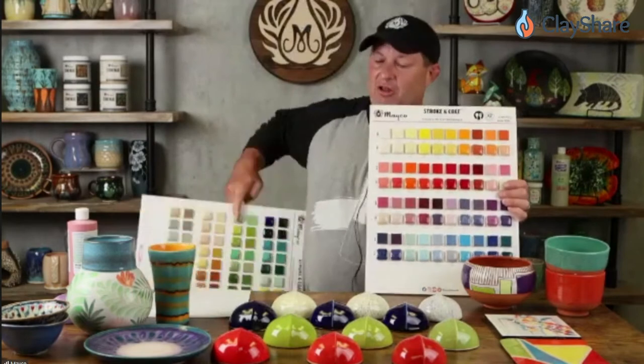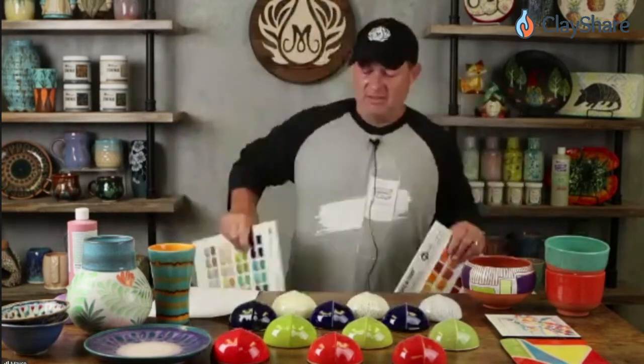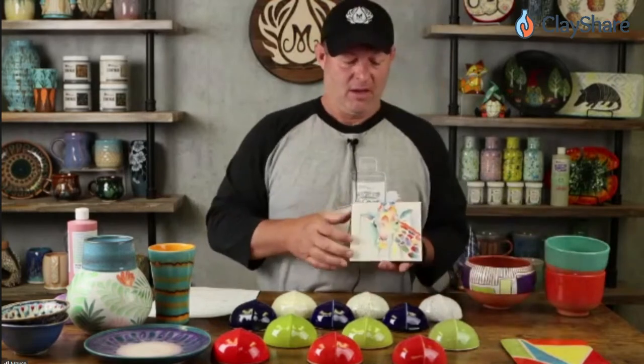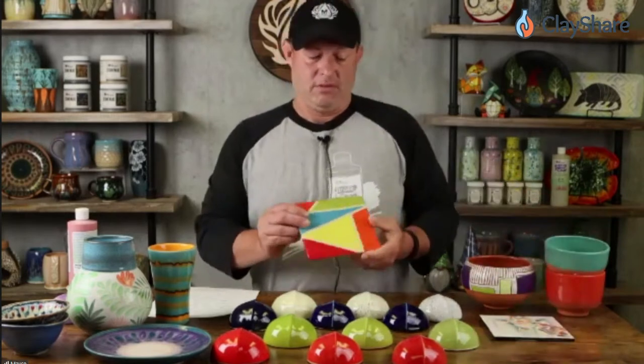We have a very large color palette, but if one of these colors doesn't fit exactly what you want, stroke and coats are 100% intermixable — that allows the artist to make their own color palette and create custom shades. They can also be used like a watercolor: thinning with a little bit of water makes them more translucent. The more you thin with water, the more translucent it becomes — same with one coat versus two versus three coats.